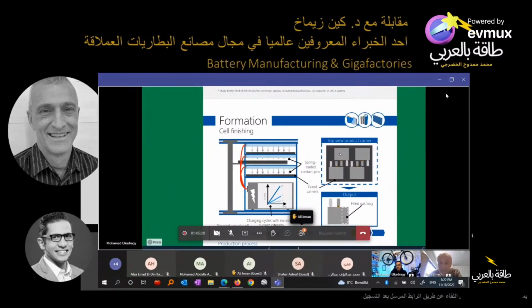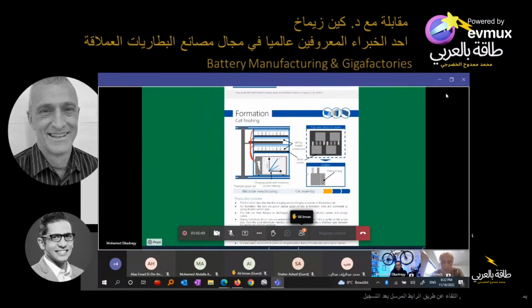In that stage, your electrolyte does some electrochemical degradation on the anode. It creates what we call an SEI layer, a solid electrolyte interphase. Some people call it solid electrolyte interface. I think phase is the correct term, but people use them interchangeably. There's no standard. This SEI layer forms. You can't stop it, but it also turns out to be a protective mechanism.